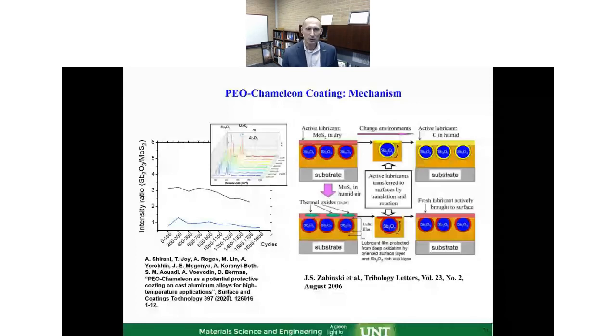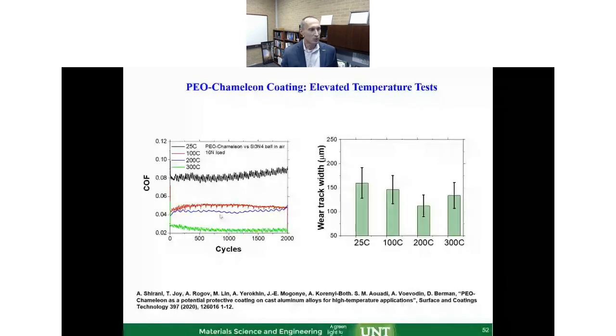But there's more to the story, because we also see, very interestingly, that not only did antimony trioxide drop down, but the wear rate and friction are dropping with the temperature. Normally we see the reverse. You increase the temperature, you have a high wear rate. And that particular combination was puzzling, that the wear rate was actually dropping. Of course, we couldn't go more than 300 C. It's an aluminum substrate here, right? So it started getting softer after that temperature and unable to support the load.